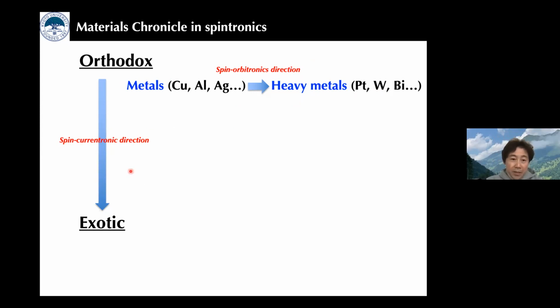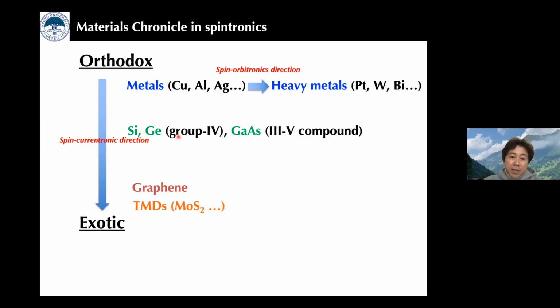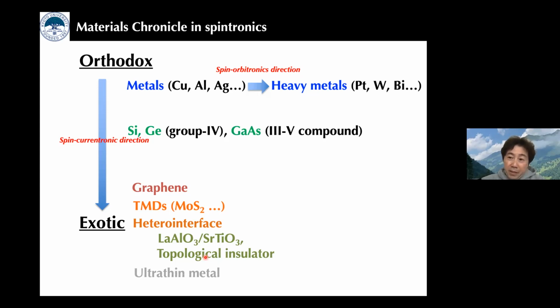Along the spin currentronics direction, in the second generation, silicon, germanium, these group IV inorganic semiconductors, and the III-V compound semiconductors, they are very important materials platforms. But more recently, in the third generation, graphene, TMDs, these kinds of atomically flat materials become much more important. And heterointerface systems, which can be formed in the oxide 2DEGs or topological insulators, are also becoming more important in the 21st century. And if I can be more brave, ultrathin metal. This is also a very important new low-dimensional material system in modern spintronics.